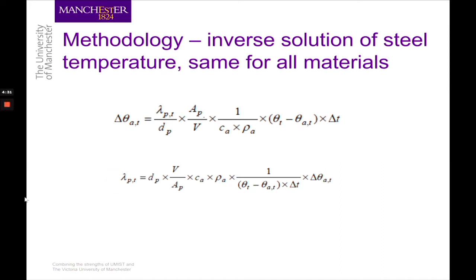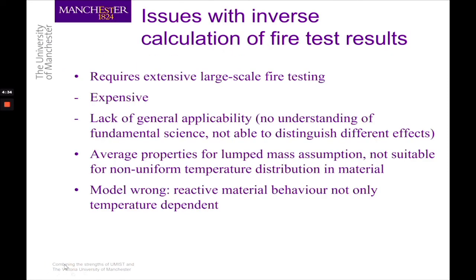But of course, this method is quite difficult. There are a lot of problems. For example, it requires a lot of expensive, large-scale fire testing, so it is very expensive and time-consuming. It is also not good enough because it lacks general applicability, because this method has no understanding of the fundamental sciences which affect thermal properties of materials. It can't really distinguish between different effects which might affect thermal properties of materials. Because of this, it is very difficult to apply this method across the board. So even if you're dealing with normally the same material, you may get different results because they have various different effects. So that's the first problem.